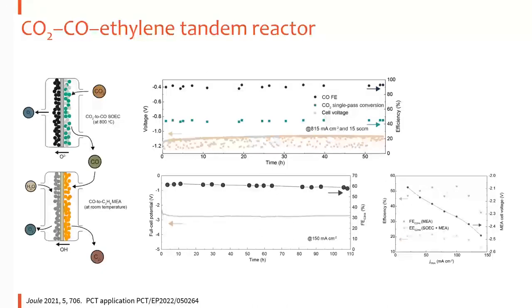The reason we use CO is that CO is not an acidic gas. It does not react with OH. So in this step, we do not have OH generated, and CO does not react with OH. So the overall process does not have the carbonate formation problem and does not have the CO2 crossover problem. And we found that using our catalyst, we can generate a similar energy efficiency for the tandem reactor, and also a very high selectivity. So this is one strategy: using a tandem reactor.